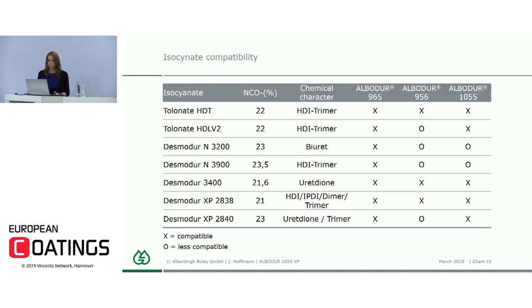As you can see, we tested the full range of aliphatic isocyanates for self-leveling floor coatings as well as for potting resins. And you can see the 1055 is relatively compatible compared to our old technology. So we have here a little bit more compatible hardness. And this we made because the molecular weight is a little bit lower than former products, in order to have really an easy and nice blending in a short time, and to have at the end, at the application side, a perfect surface.